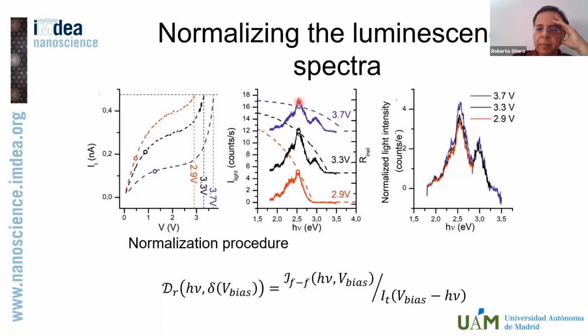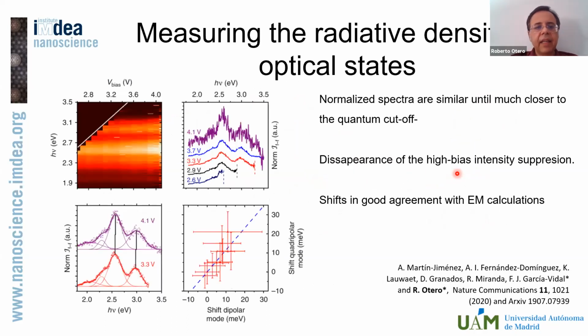Moreover, if now I divide the experimental spectra by these IV curves, what I obtain are spectra that are much more similar to each other than they were before normalization. As you can see here, the global effect on all the different voltages that we have measured is that, while there's still a slight intensity increase for higher voltages, pretty much nothing else changes. So peak ratios are the same. Peak shifts have been reduced by quite a lot, and now they correspond well with the calculations from theory, whereas they didn't do so before.